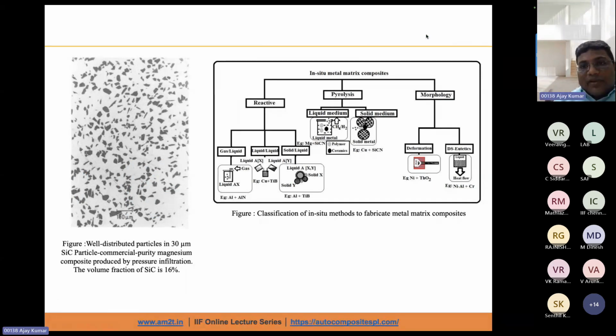Now we are talking about the manufacturing process of the MMCs. So here I am introducing the in situ MMC process. There can be ex situ process also, but if we can use the in situ process, where we can control the parameters, control the properties during the process itself, that will provide good properties for the MMCs. So we have different categories here. One is the reactive, and there is pyrolysis and the morphology. So we have different types of interfaces during this in situ metal matrix composites: gas liquid interface, liquid interface, and solid liquid interface. So we have to understand these processes as well. And then you can see here, this microstructure shows the well distributed particles in 30 micron size SiC in magnesium, and here we have used the pressure infiltration process. So I'm going to show you this process.